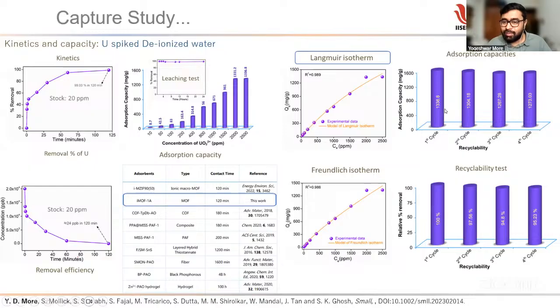So you can see the first cycle adsorption capacity was 1336. In the second cycle 1304, third cycle 1267, and fourth cycle 1273 milligram per gram. So there is a decrease, but it is marginal. If we consider this decrease over the cycles in percentage, taking the first cycle as 100% of adsorption capacity, the second cycle was 97.5, third 94.8, and fourth was 95.2.